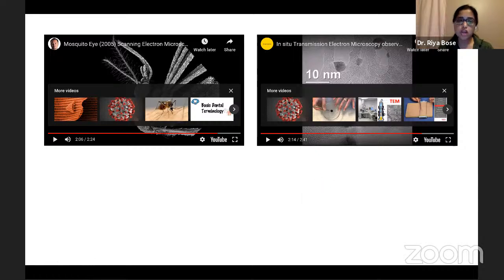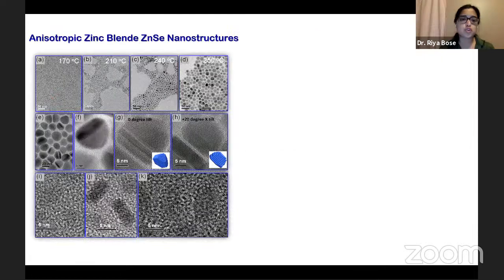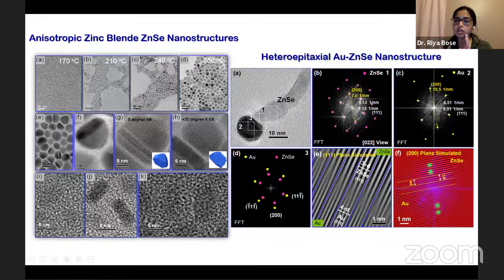So these are some of my works. So what we do also is when we are preparing a material, as I told you already, that I do shape control. How I do it, in this particular case, is I just varied the temperature from low temperature to high temperature, and I got different shapes of zinc selenide, which started with very small elliptical particles. Then it transformed into rods, and with higher temperature, I got hemisphere shaped nanocrystals, which then further grew in size. And not only can we monitor one particular material, I can also monitor the formation of heterostructures with TEM.